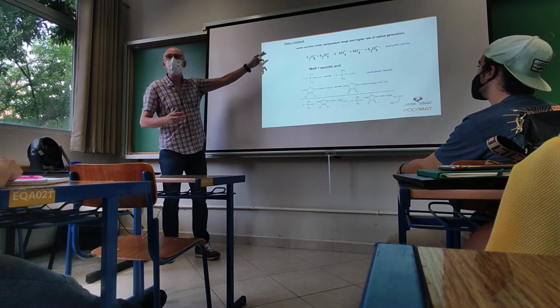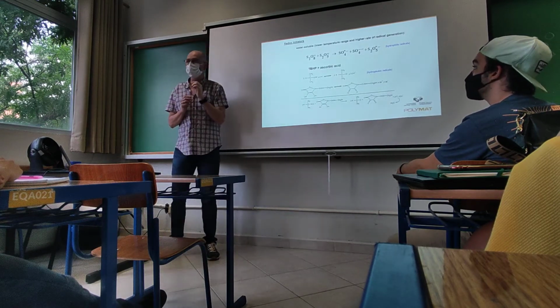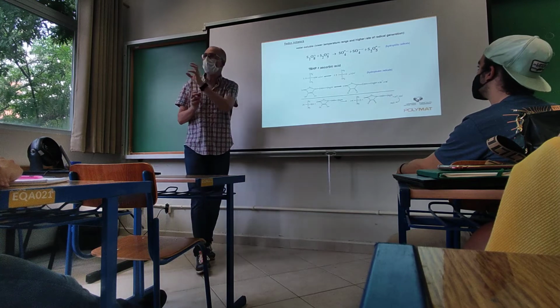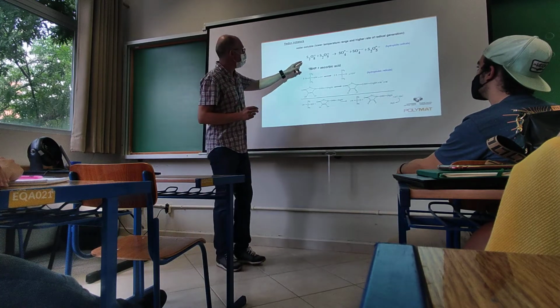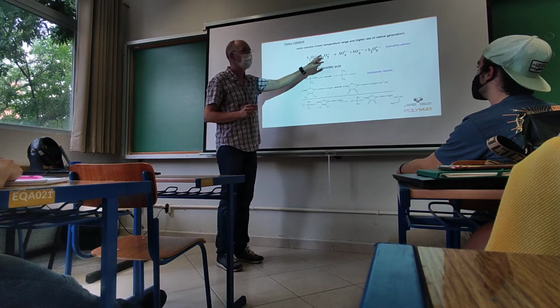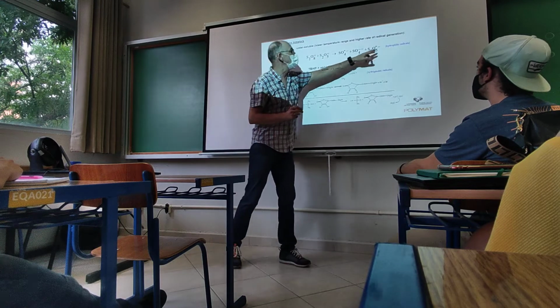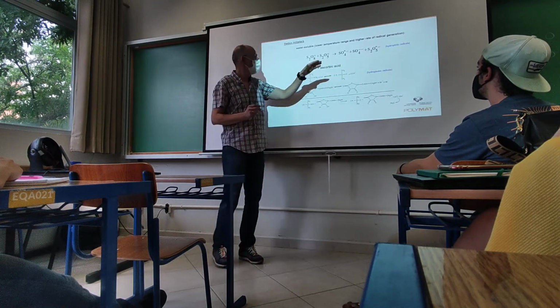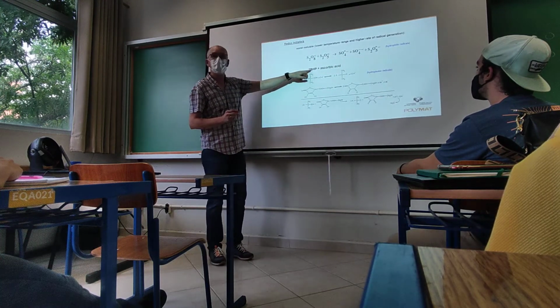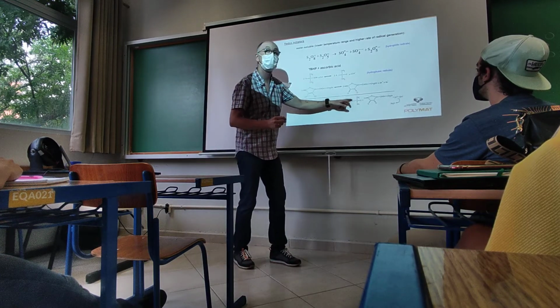Another type of initiators that are used are redox initiators. So it's redox couples. For instance, persulfates combined with metabisulfite, you form a redox couple, and you will create, in this case, hydrophilic radicals. If you combine TBHP with ascorbic acid, you will produce hydrophobic radicals.